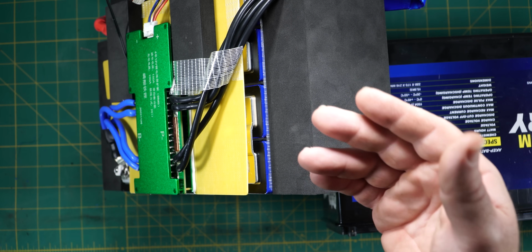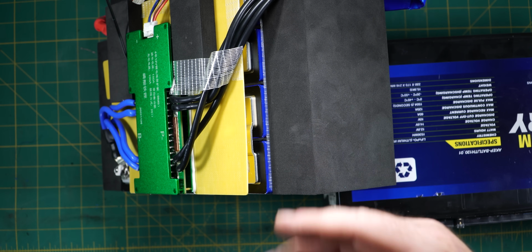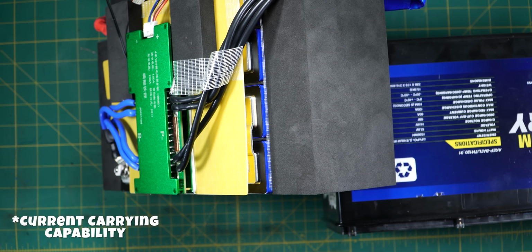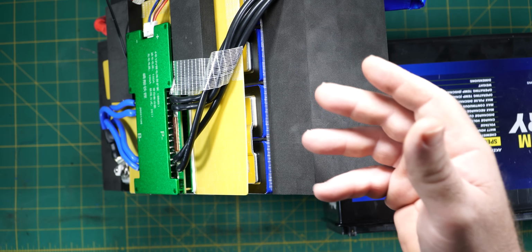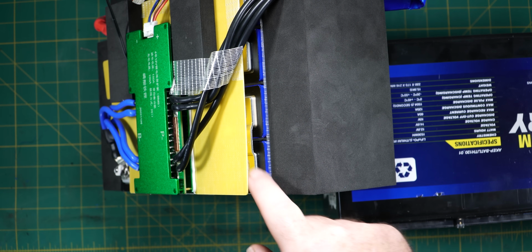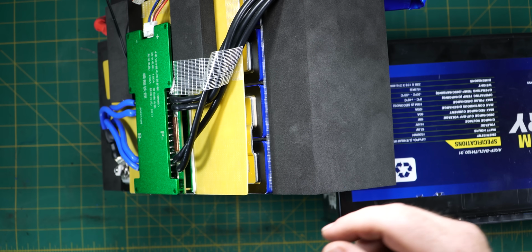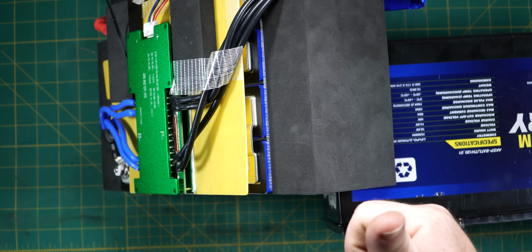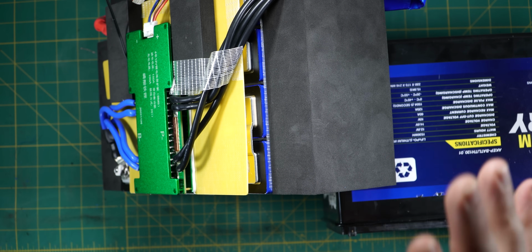If it was copper, it's roughly double. It's about 4 amps per millimeter squared. So that would give us a current capability of about 228.8 amps. So I'm pretty sure that bus bar there, she's a piece of aluminium. Rightio. Next, the temperature testing.